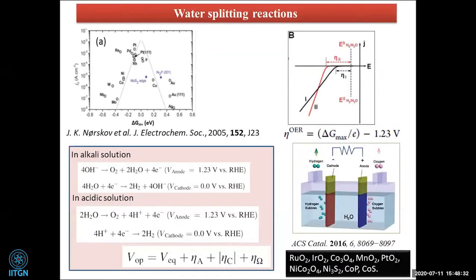And this is the most famous volcano plot, where we can see platinum is at the top. What is beneficial in this diagram is the Gibbs free energy, which is shown at 0 electron volt. So it is easier to understand that whatever catalyst metal we are using, if the Gibbs free energy of hydrogen adsorption and desorption is near 0, that is the minimum, that is the best catalyst. That's why platinum and platinum 111 are the very best catalysts for hydrogen generation from water. But what I'm going to discuss is the oxygen evolution reaction.